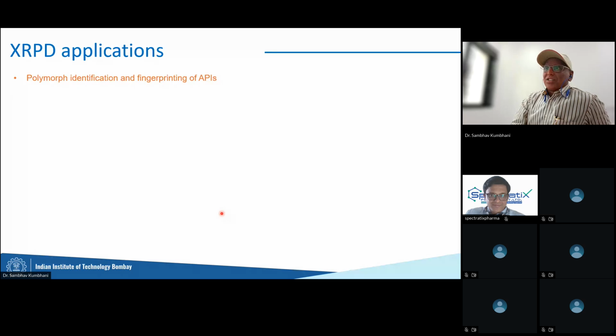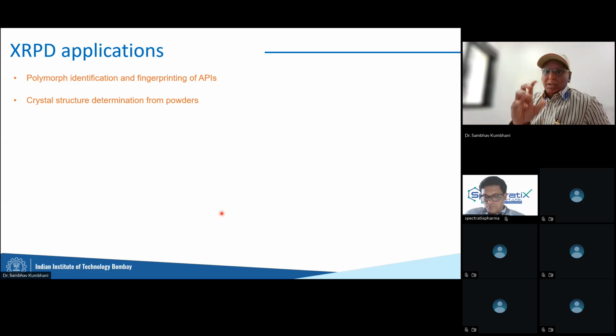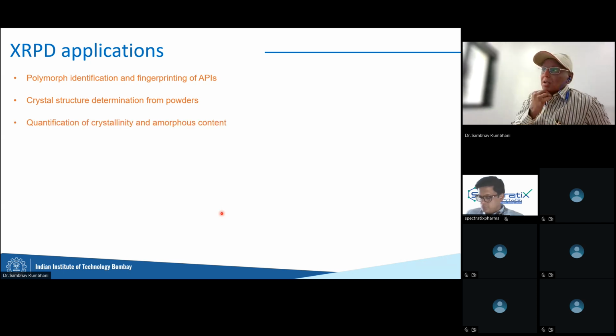Anyway, the first and most common place where XRD or X-ray powder diffraction is used is identifying a polymorph. I'll give a lot of details about polymorphs in coming slides, but polymorph identification helps you distinguish between materials of similar nature. It also helps you find the crystal structure within your powders. You could have excipients or API that are crystalline in nature, and you want to make sure they are in pure form. This is where it will help. You can obviously find how much is crystalline and how much is amorphous.